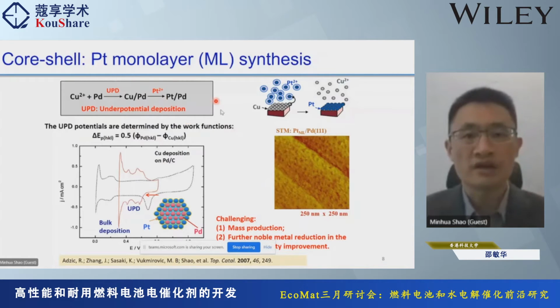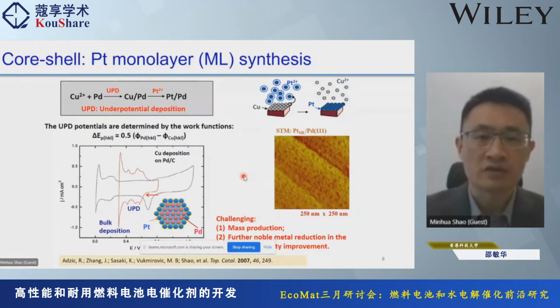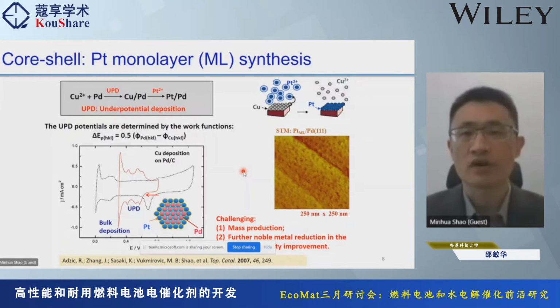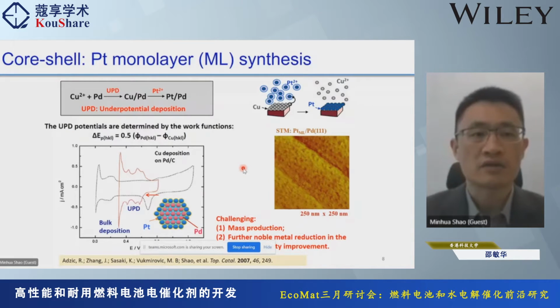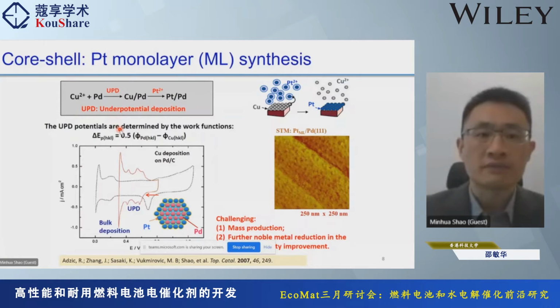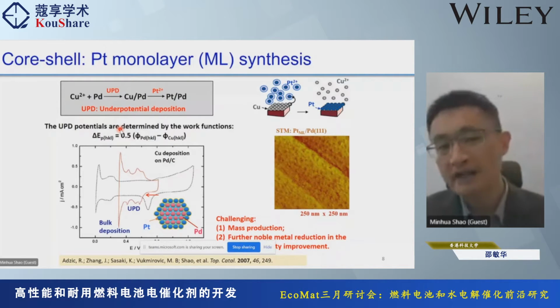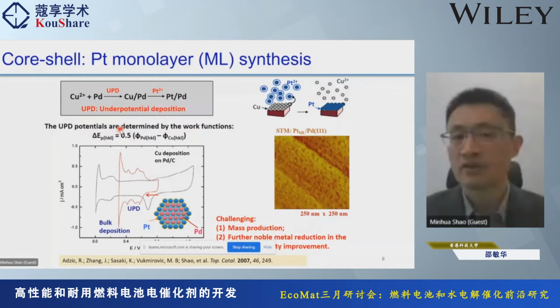With this monolayer concept, when I was still a student, we developed this kind of thing. But it's very difficult to deposit a well-controlled platinum monolayer. So we started with an underpotential deposition process with an intermediate step. We start with a material like palladium, and then deposit a copper monolayer onto it using underpotential deposition. Underpotential deposition cannot occur on just any system; it only occurs on some of the noble metals. The deposition of the copper occurs at a potential higher than thermodynamically predicted.